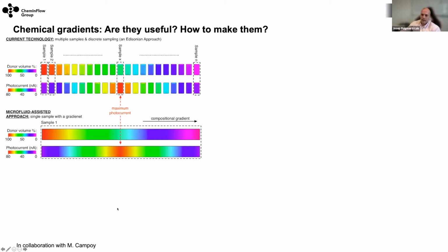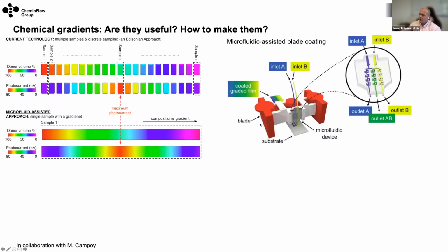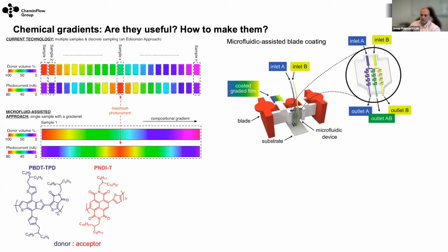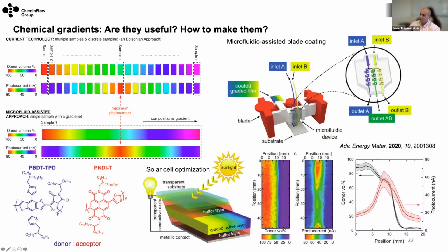And this is something that we did together with Mariano Campoy at the MAP. We assembled the microfluidic device to a blade coater. Because of the laminar flow condition, what you can achieve is a perfect mixing of two solutions. And then with the blade coater, you can have the formation of this graded film. In that case, we took very well-known polymers in the field of photovoltaics, and we flowed them through this microfluidic device to generate a film of these two polymers with a controlled chemical gradient. This is what you can see, the gradient from the donor to the acceptor. And here you have the ratios where you achieve the highest photocurrent. So this is just one example.